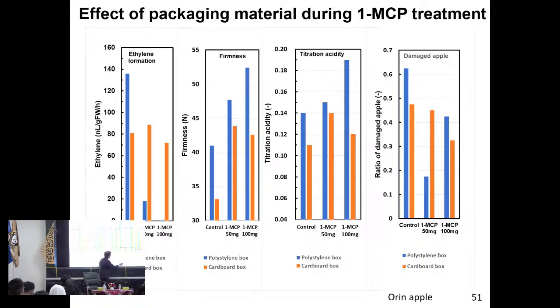But when we use higher MCP, the damage increases as expected. So 1-MCP can stop the ethylene formation, perfect. In that case, it is some kind of perfect stop, but sometimes there's a very bad effect.